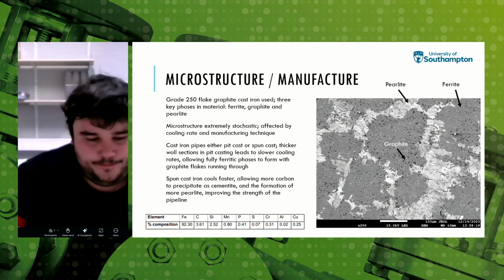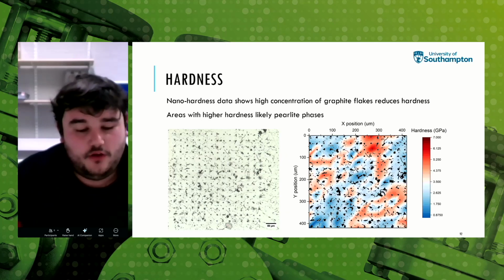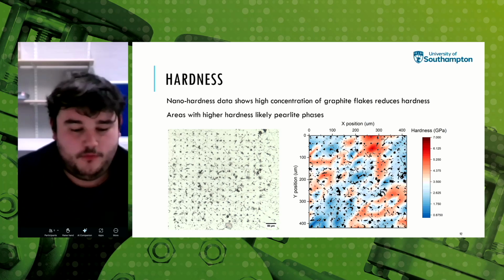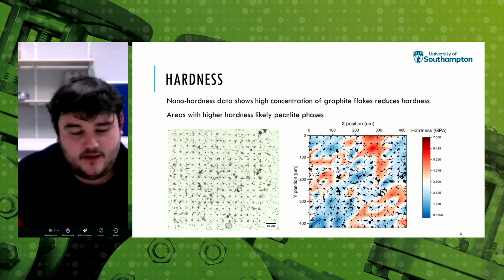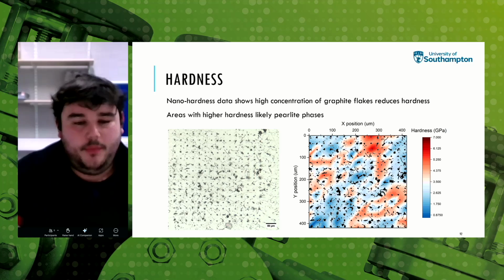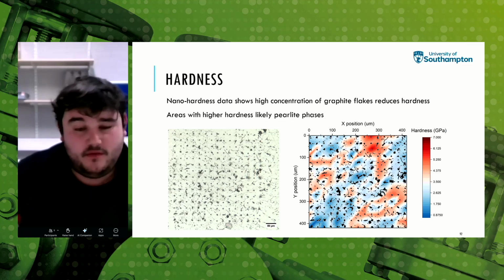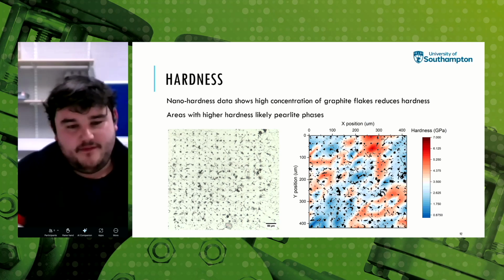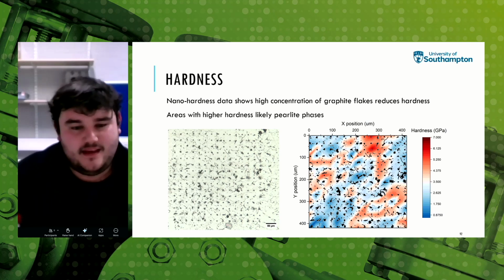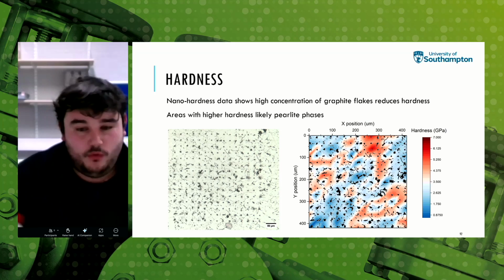The next slide, please. So we can start to look at the impacts of this microstructure and mechanical properties. We've done some nano hardness testing. So we indent a polished sample with a nano indenter that's about 4 microns wide, and measure the response of the material. So on the left, we have a map of the polished surface with the indents in. On the right, we have the results of the hardnesses overlaid with the flake structure.